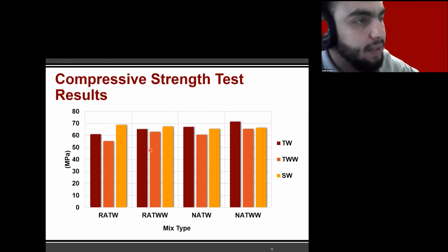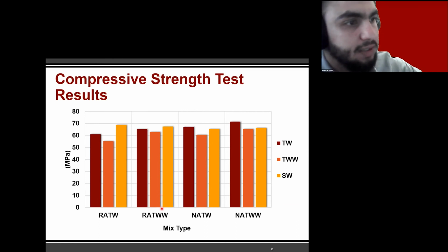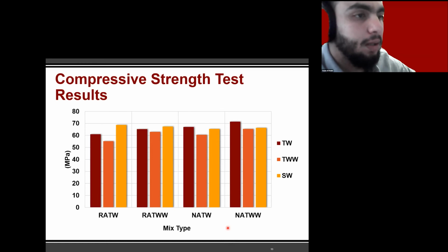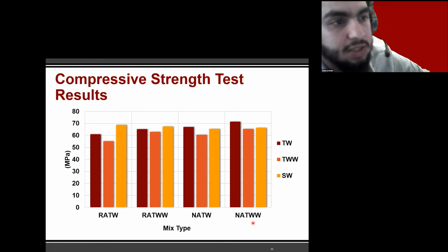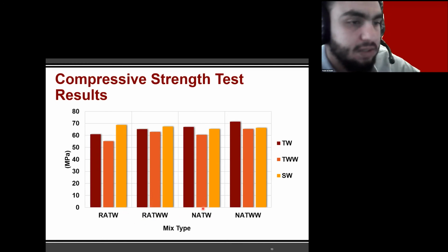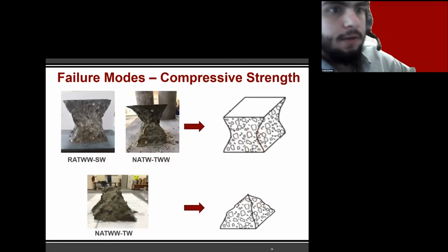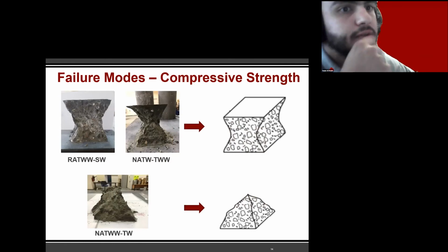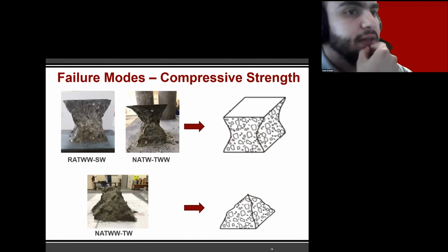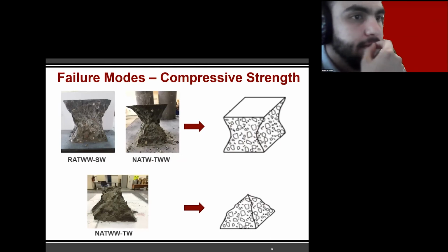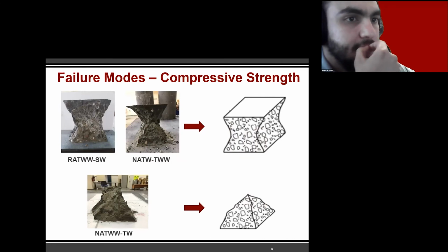And from these comparisons, it can be seen that very little difference is observed, which also complies with the literature review, which suggests that 20% replacement of recycled aggregate has negligible effect on the compressive strength. All samples were observed to have acceptable and similar failure modes to that of the control mix under compression. Some of the failure modes can be witnessed from the photos shared in this slide.